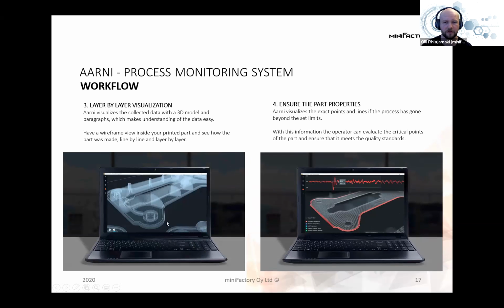And in this software, you can go through each line, each layer, and see the exact parameters that occurred during that layer or that line. What makes this really easy to use is the visualization the software offers. If there are some deviations in temperatures and the temperatures have crossed the set limits, the software visualizes these deviating sections of the part by a different color. From the color, we can see that, okay, for example, extruder temperature has gone below the set range. And in the software, we can see the exact lines.